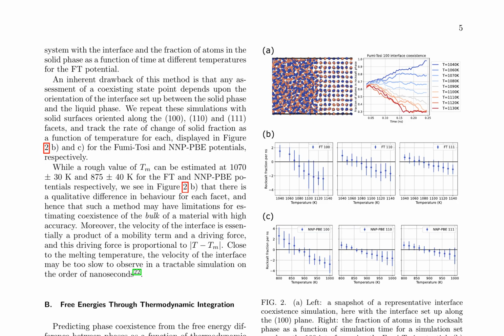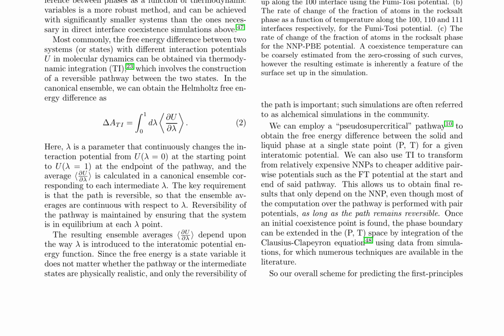The authors discuss two approaches to predict the solid-liquid phase coexistence of materials. They first describe direct interface coexistence simulations, which have limitations due to the dependence on the orientation of the interface and the slow velocity of the interface close to the melting temperature. Alternatively, they employ thermodynamic integration, which involves constructing a reversible pathway between the two states. This method is used to predict the phase coexistence from the free energy difference between phases as a function of